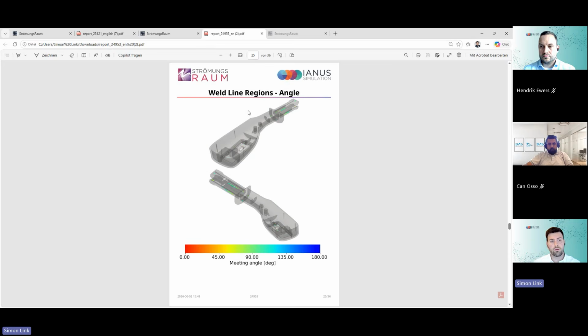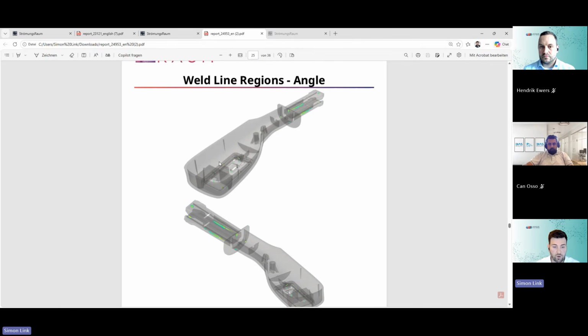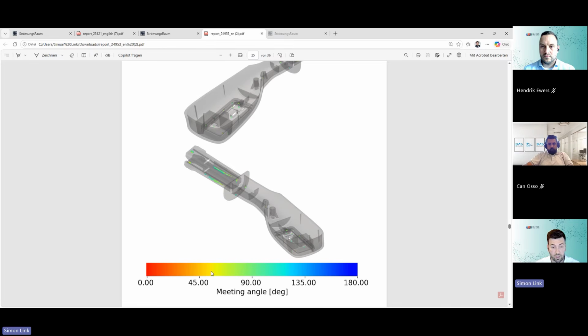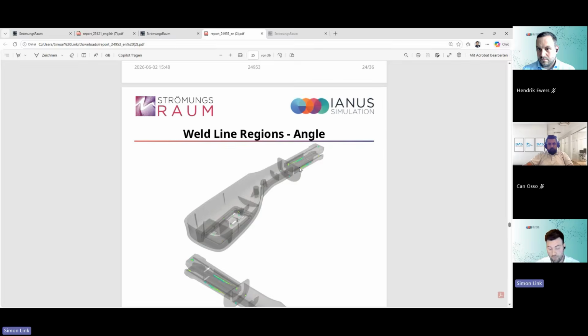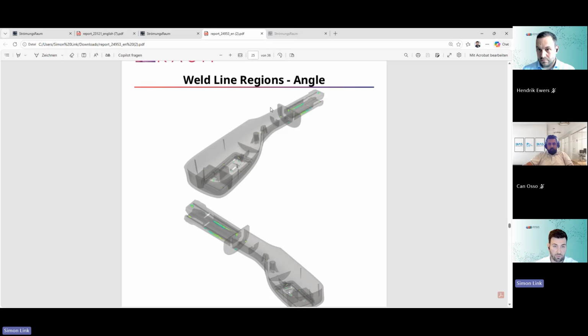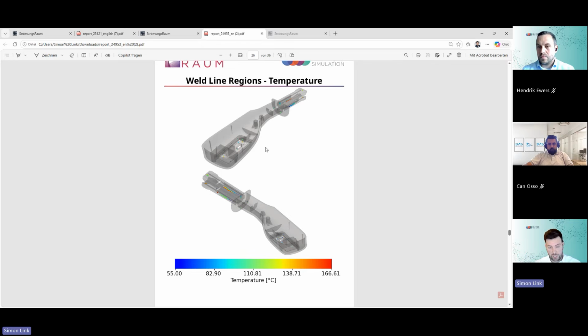And here you can see the plot for the weld line. So this could be a potential issue, as it was mentioned here in the recommendations. So what we see here is, let me zoom in a little bit. We have the weld lines that are visible, and we also see the angle at which these weld lines are formed when the melt fronts are connecting. So when the angle is too low, this could, as already mentioned, lead to a weakened strength of the weld lines. And we can also evaluate this in combination with the temperature of the weld lines. So we see here the temperature of the weld lines when they were formed. And we can evaluate this together with the information of the connection angle of the weld lines, and then make a better estimation about the strength of the weld lines.